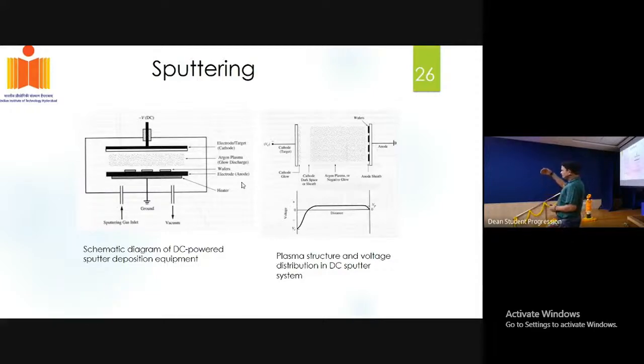These argon atoms, these argon ions, you cannot call them atoms. These argon ions will come very fast and they will transfer the momentum to the atoms which exist in the target material. So the moment there is a momentum transfer between the argon ion and the atoms that exist in the target material, these atoms will eject and will go and deposit on top of the substrate material. It's basically the ejection of the atoms of the target material by the argon ions in the plasma.